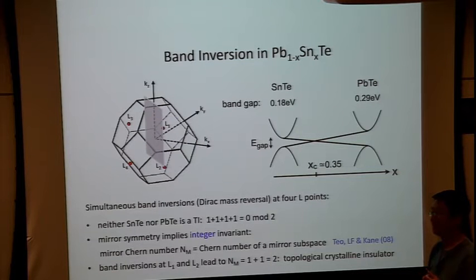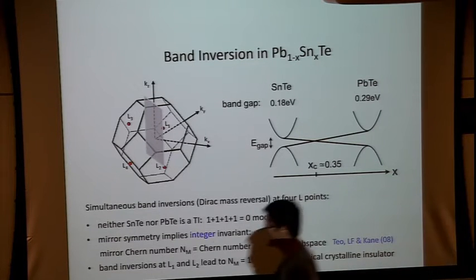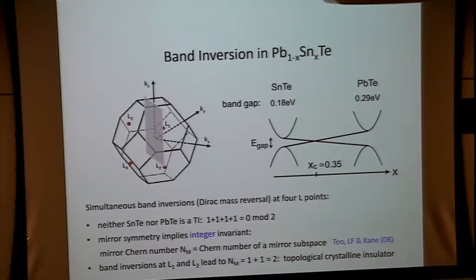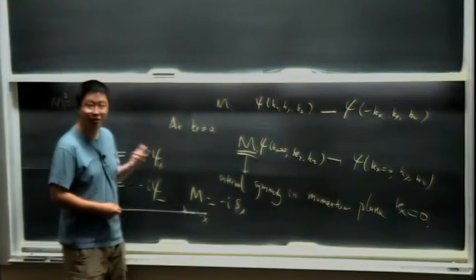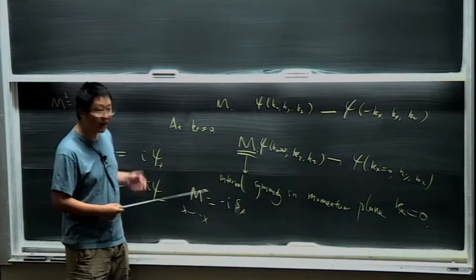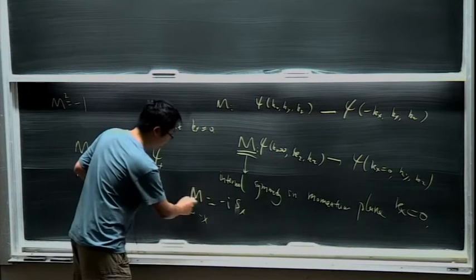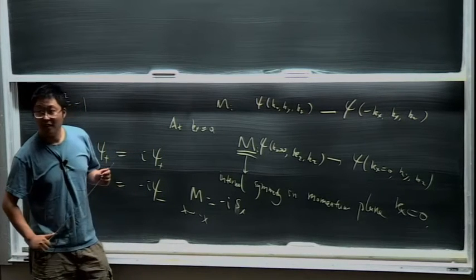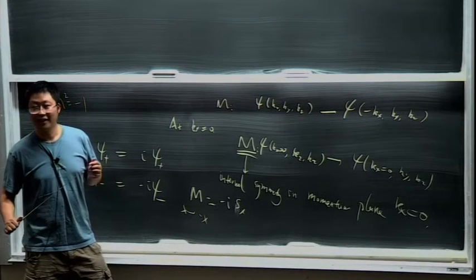Exactly. So what actually happens? The action of M, in terms of its action on the spin, is represented by minus i sigma_x. So this is reflection x to minus x. You see that if the spin is pointing in the x direction, reflection does not change the spin eigenvalue. But if it's y and z, it will flip the spin. And with this, M squared is minus 1. There's no complex conjugation. That's very important. It's a unitary symmetry, a unitary spatial symmetry.